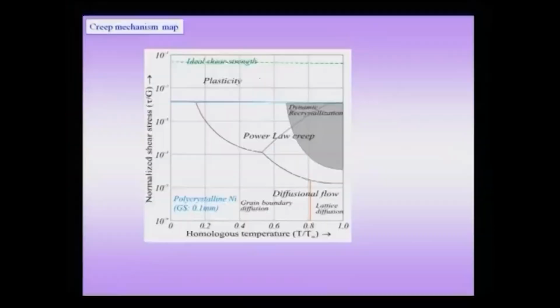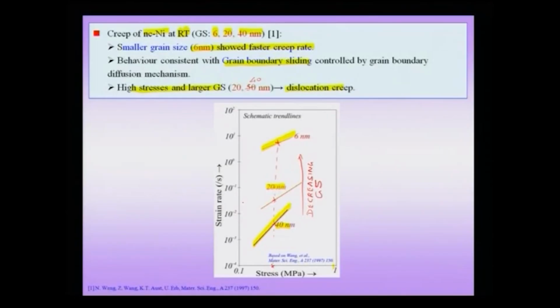And we had noted some of these regions in the creep mechanism map, which we had seen earlier. In the creep mechanism map, we had noted that it is usually in the higher stress region, which is in this axis, that you tend to observe dislocation creep, and in the low stress region you tend to observe diffusional creep. So, you see that this is the region of diffusional creep, and in the higher stress region you actually obtain dislocation creep. So, this is a very interesting study.